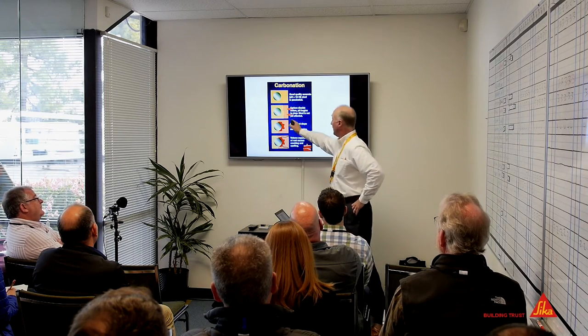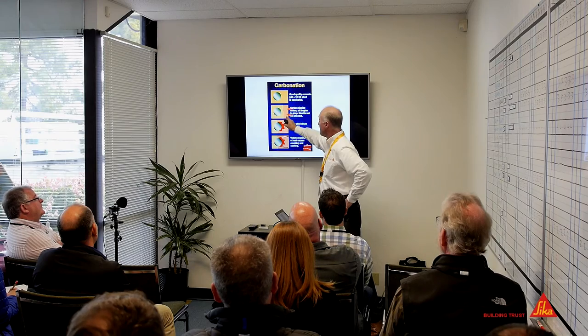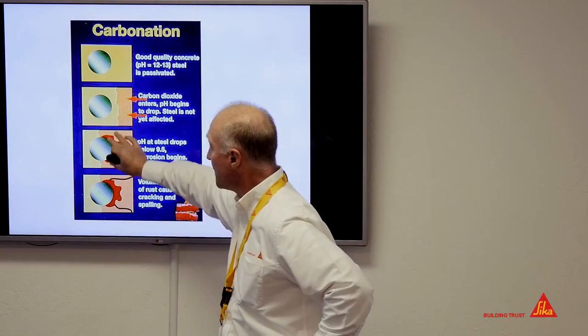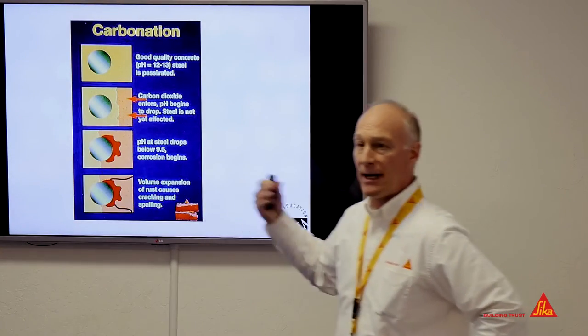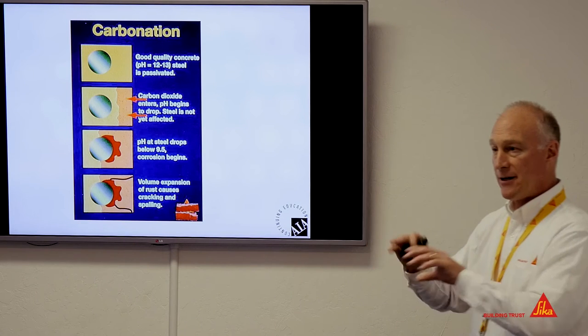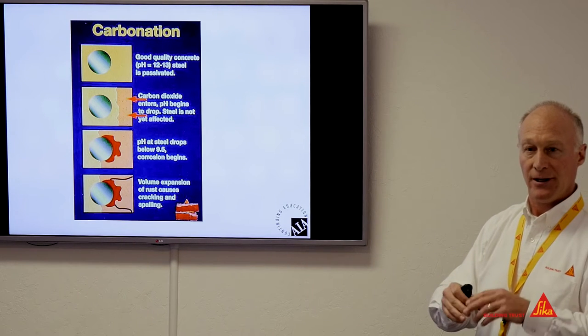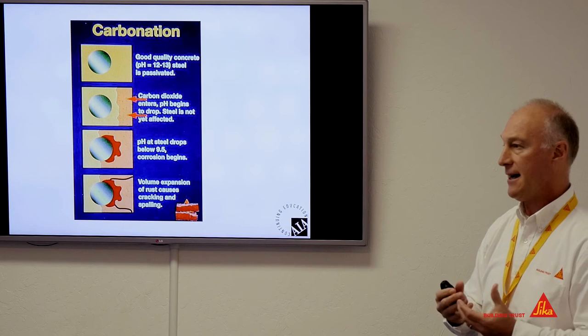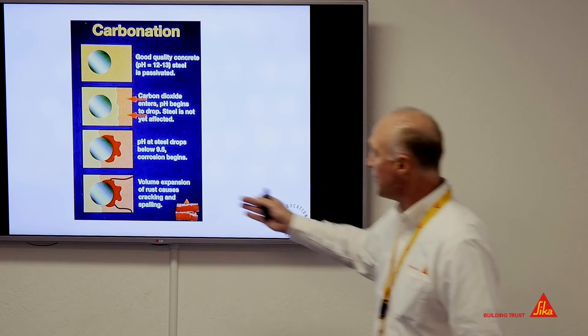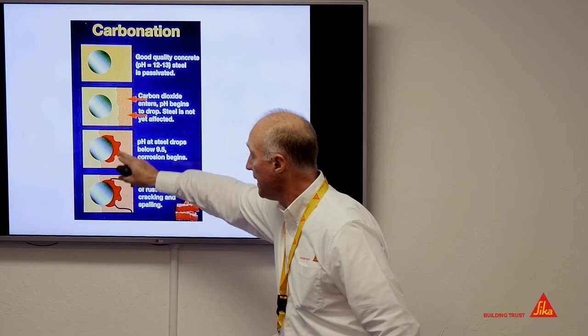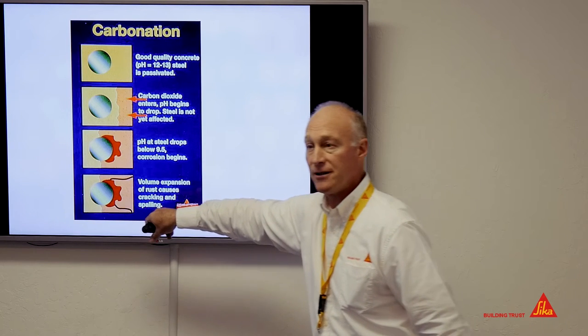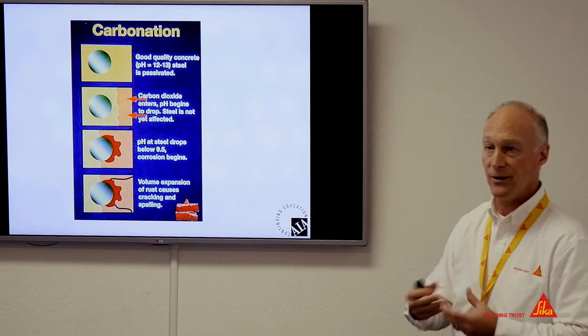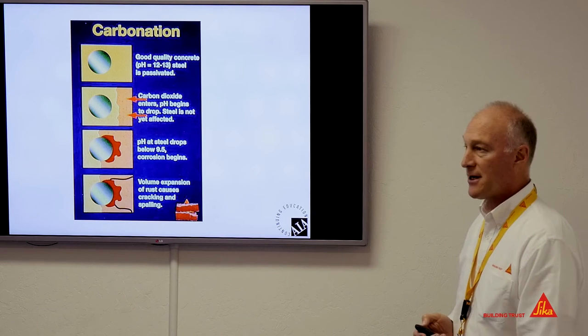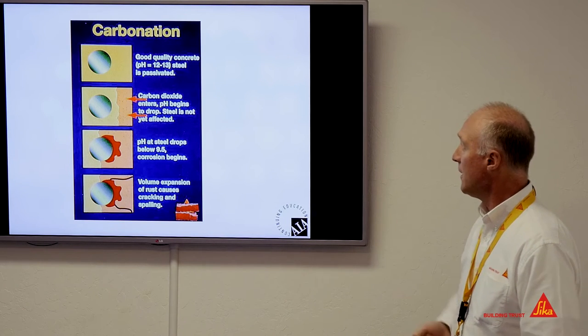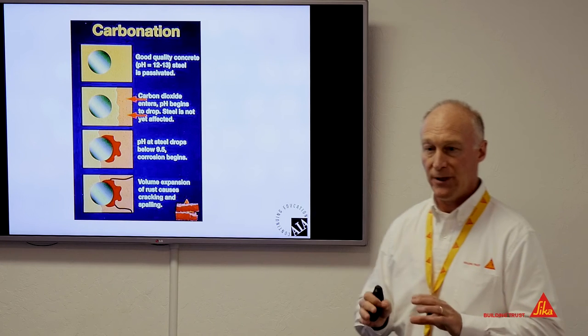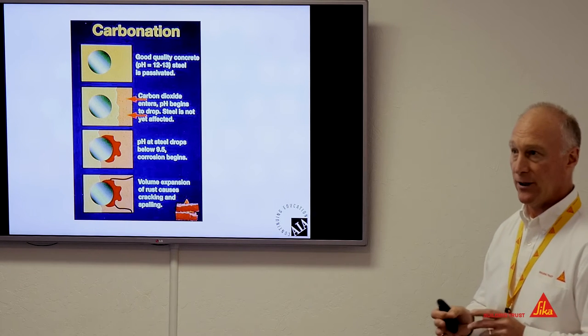Yep. And now this is not necessarily a problem, but eventually this gets to the steel. If you think back a few slides, now that it has gotten to the steel, the passive film is no longer struggling to stay intact. Oxygen and moisture are present, corrosion begins, and then as that corrosion continues, it expands, cracks, and swells. That's basically the process in a nutshell. So those two, carbonation and chlorides, are some of the biggest culprits that we're faced with when it comes to concrete repair.